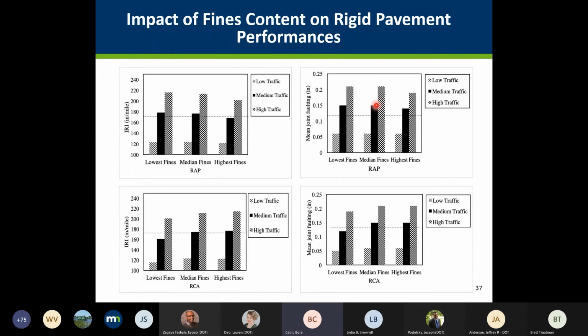And on the other hand, the story changes again with the rigid pavements, that with an increase in fines content, actually we see some decrease in the IRI with the RAPs, while we didn't see that much change with the RCA with an increase in fines content, especially at high traffic conditions. IRI even increased more. And for the mean joint faulting, we seem to see again the RAP material with higher fines perform a little bit, I mean, not noticeable, but somewhat at high traffic condition, improved, decreased the joint faulting distresses a little bit, but still it exceeds the mean joint faulting values considerably at high and medium traffic conditions.